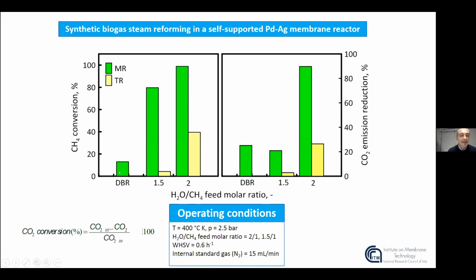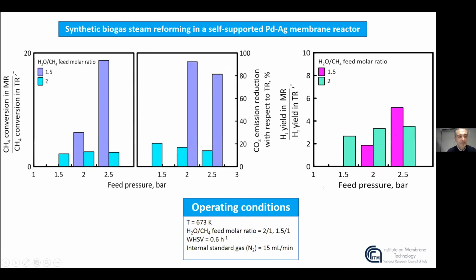And in one case, we realized also the dry reforming of biogas in the membrane reactor, getting a conversion a bit higher than 2%, and the CO2 emission reduction equal to 30%, and the best one was in the membrane reactor at almost 90%. However, by comparing the membrane reactor with the equivalent traditional reactor, it's possible to observe how